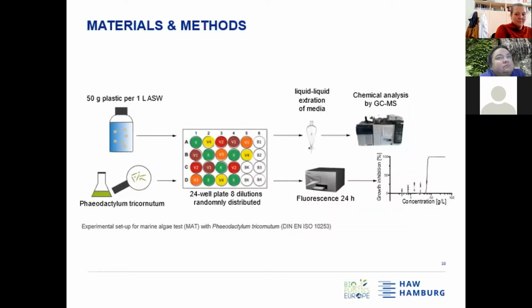So on this sheet, you can see the experimental setup for the marine algae test with Phaeodactylum tricornutum. In contrast to daphnid tests, we only carried out leaching tests with the algae because for contact testing, it is necessary to introduce the plastic material directly into the algae culture, and we are observing the fluorescence of the algae. So if there are plastic sheets or particles in the culture, the fluorescence is weakened by them. So we only tested leachates of the bioplastic materials with the algae. We tested concentrations of a maximum of 50 gram bioplastic per 1 liter artificial seawater.